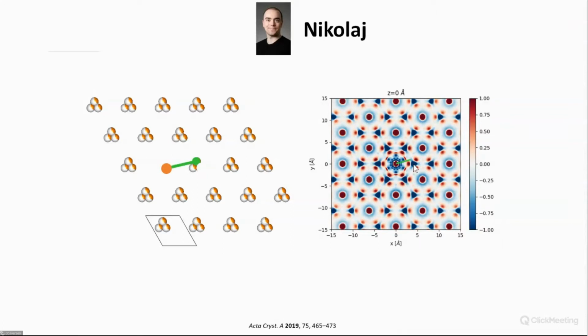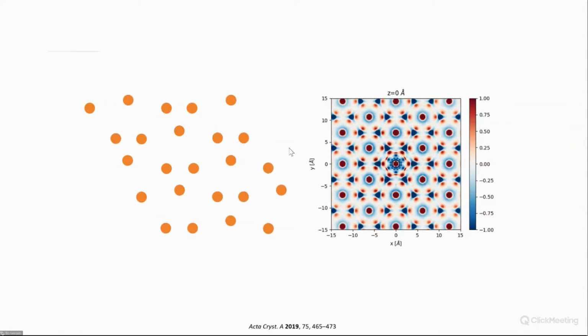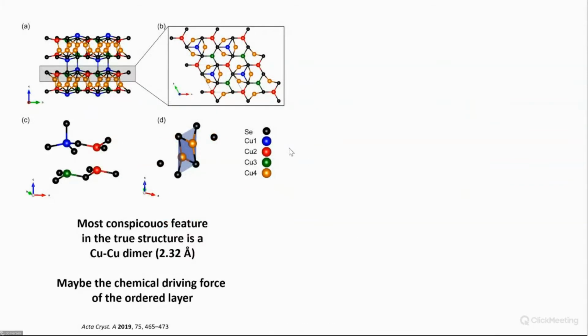How about this side? It's also negative. So that's not where it is. But on this side, you have a positive. So there's more density than the average. So this is where the copper atom is. And this way, Nikolai could solve the whole structure. This is for this copper atom, the layer structure, and he could do that for all the layers. It turns out that copper selenide is basically just these slabs that are perfectly ordered, and then these slabs are disordered along the c-axis. So they can be inverted and they can slide. But this is the true local structure of copper selenide.